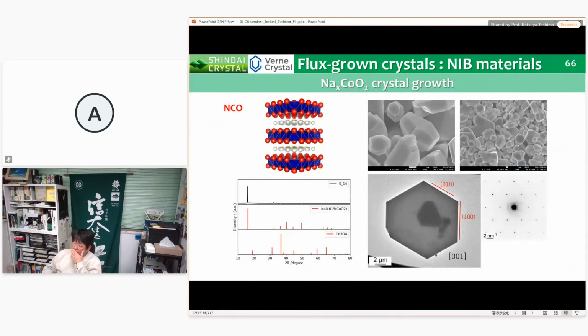As a result, for sodium cobaltate, barrel-shaped low aspect ratio crystals were uniformly obtained, as shown here. The XRD pattern also confirmed that the P2 phase was obtained. Furthermore, TEM measurements show that the crystals were single crystals or primary particle crystals with uniform orientation.